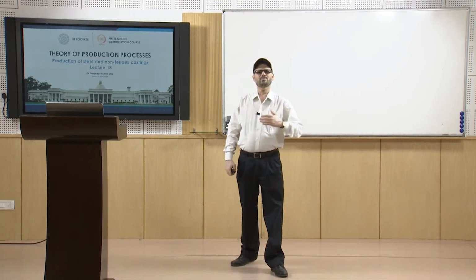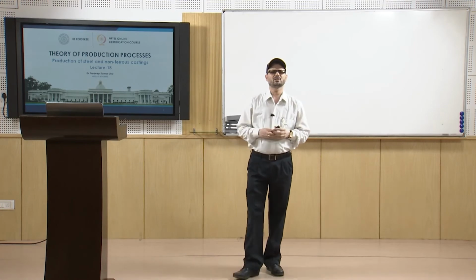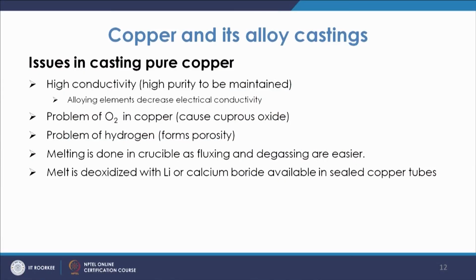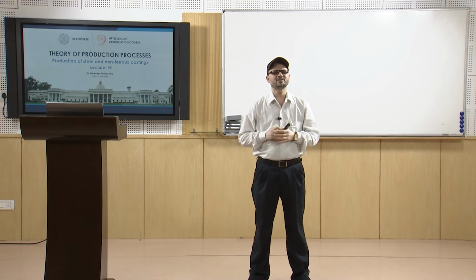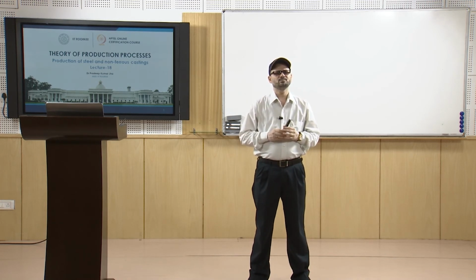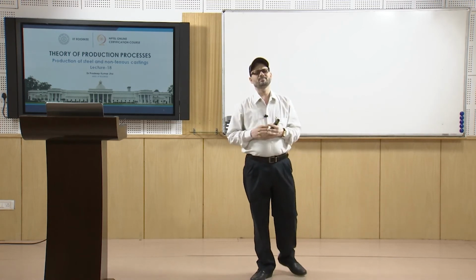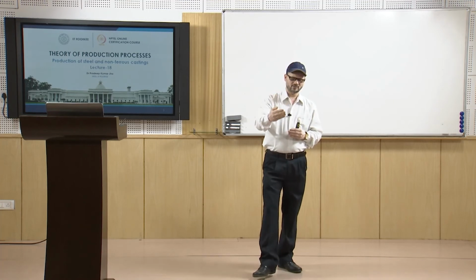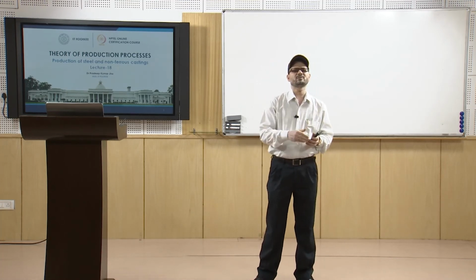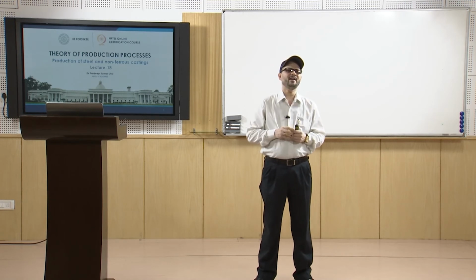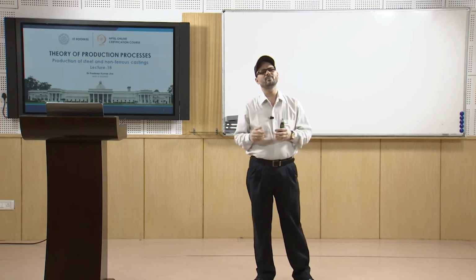Now, coming to particular materials like copper. In the copper, basically the challenge is about the higher conductivity. This is the challenge which has to be faced, because the temperature gradient is not maintained that way, because the conductivity of the metal itself is very high. So, what happens when we make the alloying and you make the alloy of copper with some other material, then the main aim of having high conductivity is sometimes compromised.